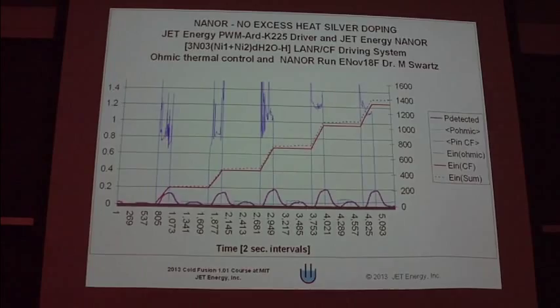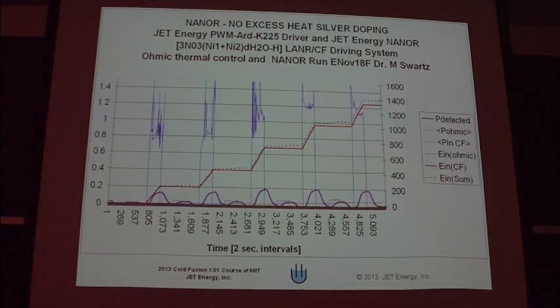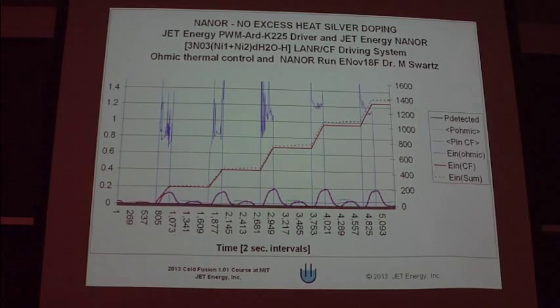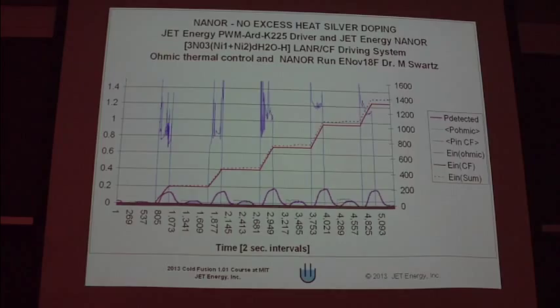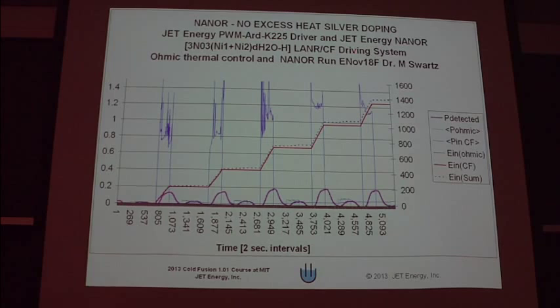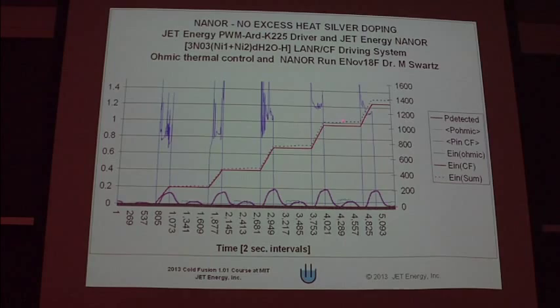Here's our thermal power spectroscopy — we're looking up to about 20,000 seconds, about a third of the day. Here's our ohmic control, and with the cold fusion device here's our input and here's our detected output. If we take the ratios, that's our energy gain, and in joules we're getting out about 500 extra joules over a third of the day using the series three nanor. This is a dry two-terminal device that we ended up running. We also found the nanor explorer is incredibly effective for evaluating additives. We found that silver doping made the excess energy disappear.